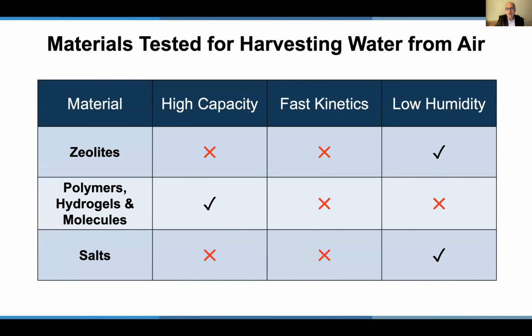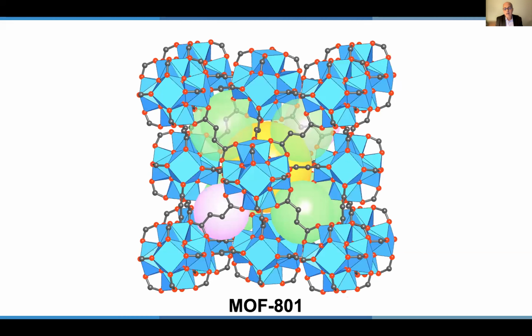So there aren't very many materials out there other than MOFs that work. There are materials such as zeolites, polymers, salts, they all take up water, but they have one problem or another that prevents them from being economical. For example, you need to have high capacity. Some of them don't have that. You need to have fast kinetics. Water has to go in and out with great ease so that you can harvest lots of water over time. You absolutely need to be able to trap water from air of low humidity. That's where it's most needed. And as I said, if you can do that, then you could harvest water anywhere in the world at any time of the year.